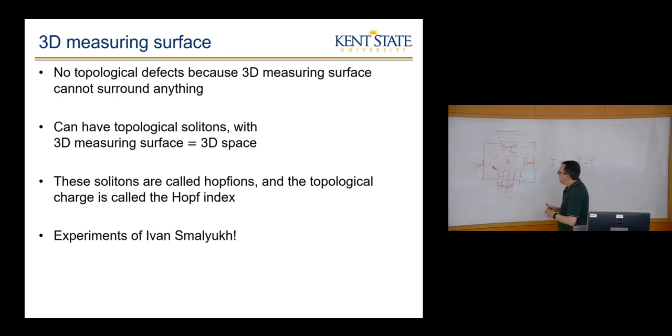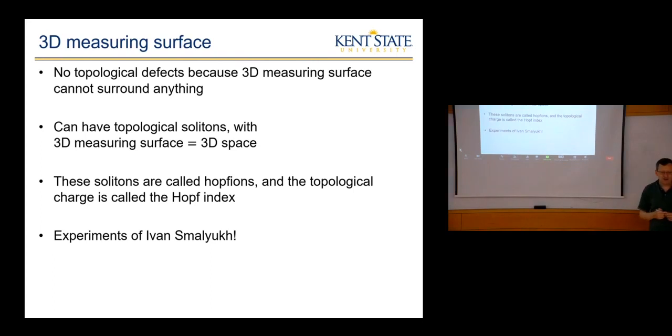And so this would look like a pattern of brushes in an optical experiment, that you'd see these regions that are bright versus dark. And you would count how many bright regions there are. And you would say, oh, there are two, and two is associated with half charge. If it would be a charge of plus or minus one, you would see four bright brush regions and four dark regions. And then you could tell what is positive or negative by rotating the polarizers and seeing how the whole pattern rotates. So this is the simplest experimental technique. There are lots of other versions that go beyond that.